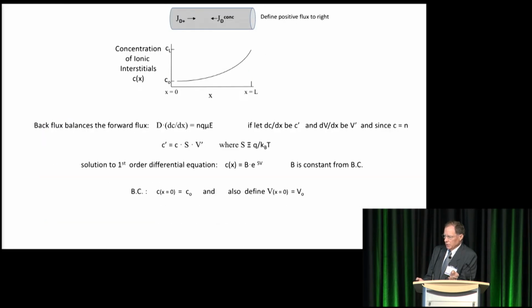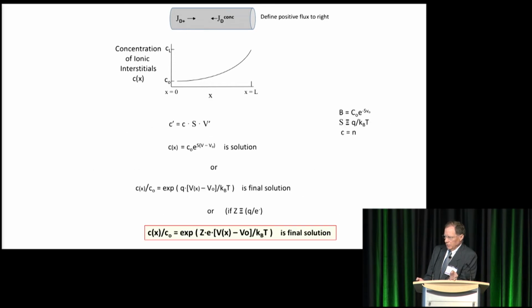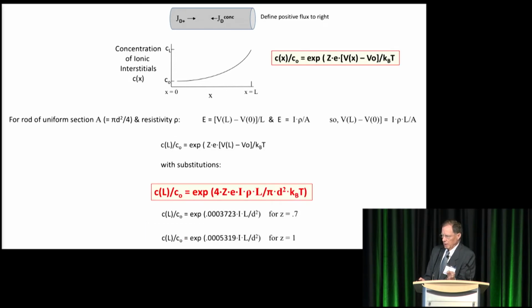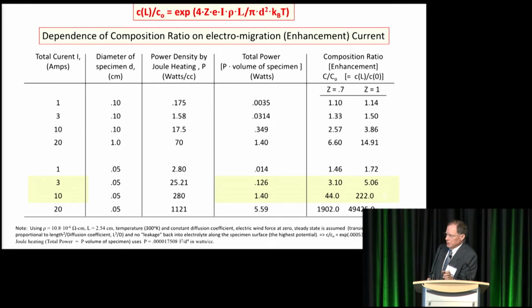If you solve that differential equation using the boundary conditions, the solution looks like this, and replacing the voltage with current, you get the final solution, and plugging in the cross-sectional area as a diameter, you get this solution. This is a ratio of the concentration at the far end as a function of the other end of the specimen. The bottom line is that there's a substantial contribution, enhancement. If this enhancement were only 0.3 or 0.4, I'd consider it a successful mechanism, but it's much more than that.